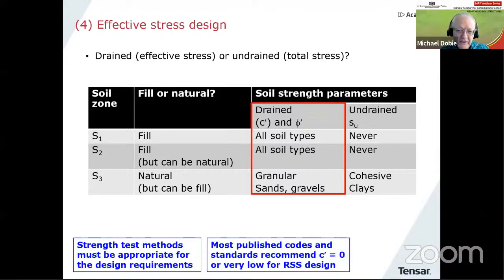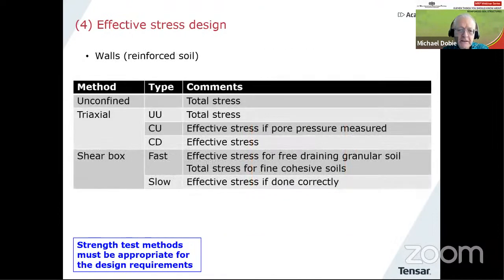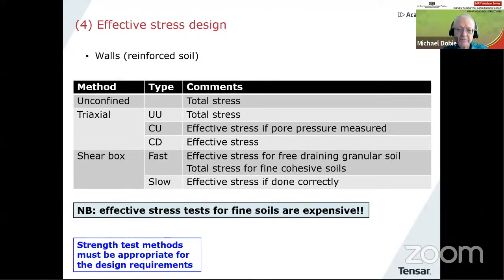In fact, why do I put C dashed in brackets? Well, most published codes and standards recommend that you would use C dashed is 0 or a very low value for reinforced soil design. Now, here's a slight problem, because when we look at available strength tests that you might use to determine these properties, we are rather limited, especially for fine soils. So if we're talking about fine soils, and we're often using fine fills here in Indonesia and many other parts of Southeast Asia, then we basically have a choice of triaxial CU or CD tests or slow shear box testing. And the slight problem is that effective stress tests on fine soils tend to be expensive, and this can lead to difficulties.